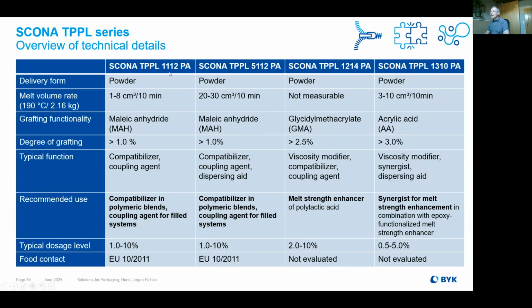Here are the different grades which we have. So you see that the 1112 and the 5112 are both based on the maleic anhydride grafting. The difference is the 1112 has a lower melt compared to the 5112. And both products are quite often used as a compatibilizer between different polymeric blends and could also work as a coupling agent for filled system. So we did this both grades just to help the people which are working in different MFR values.